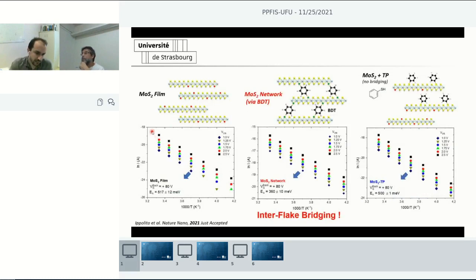If we plot an Arrhenius plot, the logarithm of the current as a function of the inverse of temperature, we can extract the activation energy for this transport. And we observe the activation energy is around 500 millielectron volts for films, and it decreases to 300 millielectron volts for networks. Once again, showing that the transport becomes facilitated.